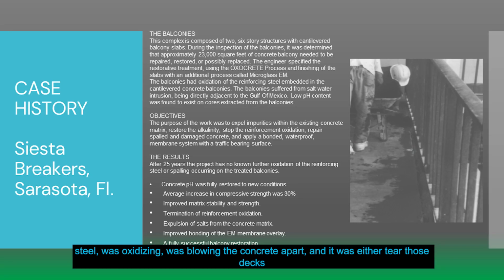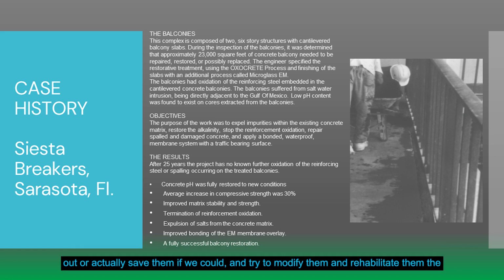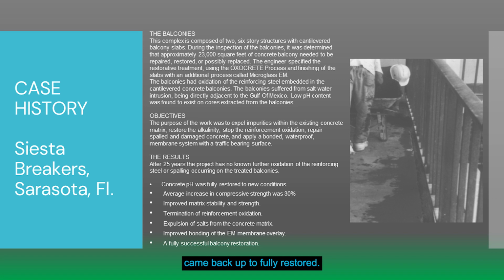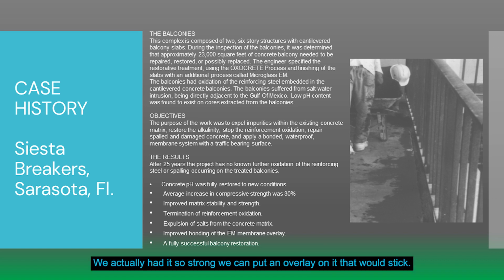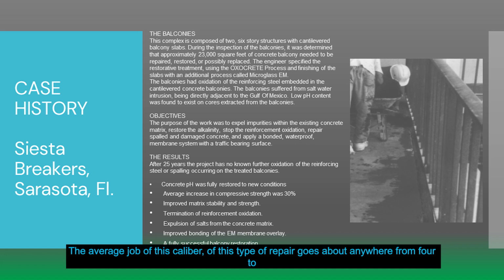The steel was oxidizing, it was blowing the concrete apart, and it was either tear those decks out or save them if we could and try to modify them and rehabilitate them the best we can. So basically the results of our process were that the pH came back up to fully restored. The increase in compressive strength was over 30%. We stopped all the steel from rusting. We actually had it so strong we could put an overlay on it that would stick. It's lasted to this day without any more major repair.